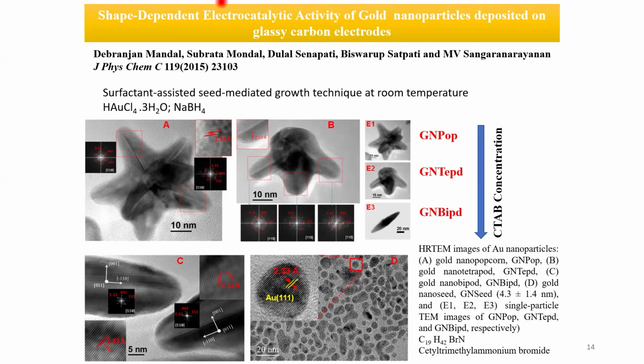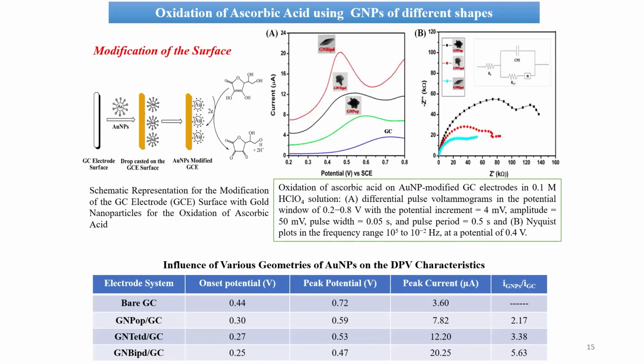Now, what is interesting is that this geometry has a profound effect in electrocatalysis. That means whether your geometry is popcorn or tetrapod, the reaction rate is different. You can see here. Geometry is dictating electrocatalytic efficiency. First time it was shown here, where electrode geometry seems to influence the rate constants. Right? That is very important.